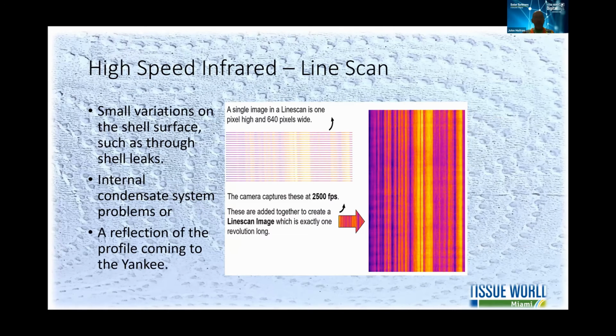And then high-speed infrared imaging or line scanning. This will check for very small variations on the shell surface, such as a through shell leak. And sometimes through shell leaks occur during operation, but you shut it down and you can't find it. This is a tool that would find a through shell leak. It can also, as the OTR, can determine if there's internal condensate system problems. Or it can also fool you because it can be a reflection of a poor profile of a sheet coming to the Yankee dryer.